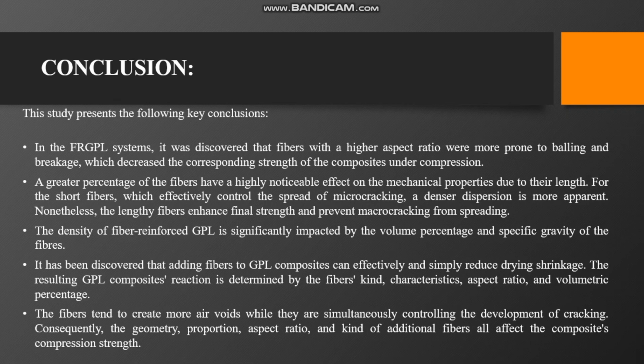In the fiber reinforced geopolymer systems, it was discovered that the fibers with a higher aspect ratio were more prone to balling and breakage, which decreased the corresponding strength of the composites under compression. Fiber percentage significantly affects the mechanical properties, with short fibers controlling the microcracking and long fibers enhancing the final strength and preventing macrocracking. The fiber volume percentage and specific gravity impact the fiber reinforced geopolymer density. Adding fiber reduces the drying shrinkage in geopolymer composites, with fiber characteristics influencing the composite reaction.